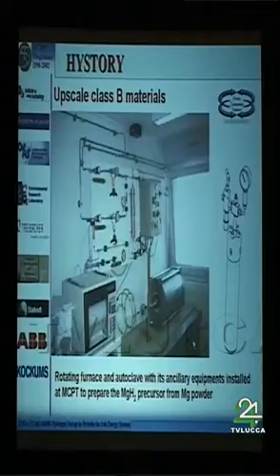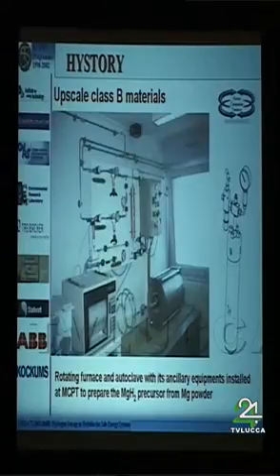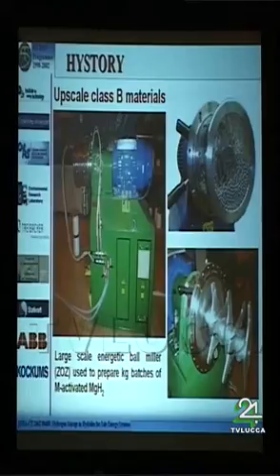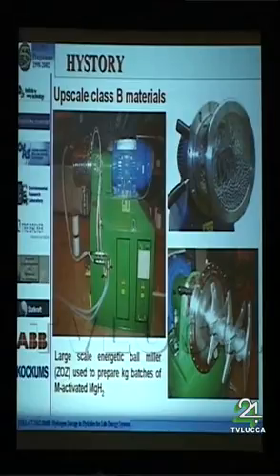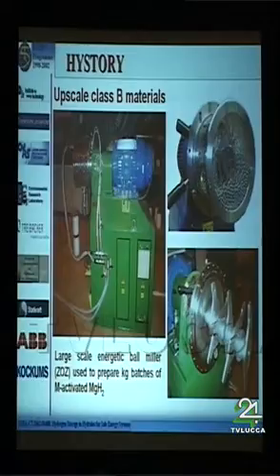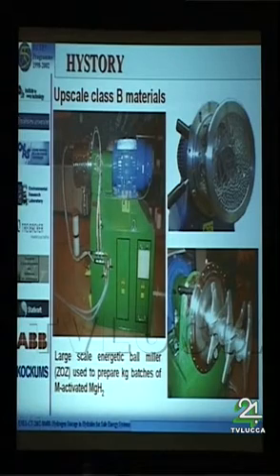For upscaling the second class of metal hydride, magnesium hydride, we work with the MCP company, a French company. The work is done in two steps. First, it is necessary to prepare the magnesium hydride powder. We have a rotating furnace, now quite automated, to produce this powder in mass. After that, we use a very energetic ball miller to upscale the production. For example, we now work with 1 kilogram per batch, but it's possible to prepare several kilograms of well-activated material.